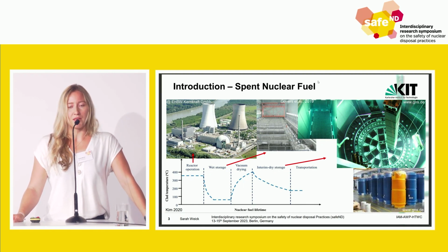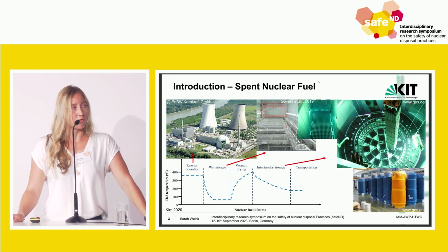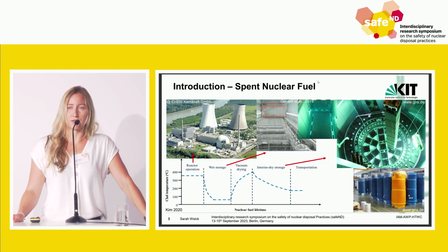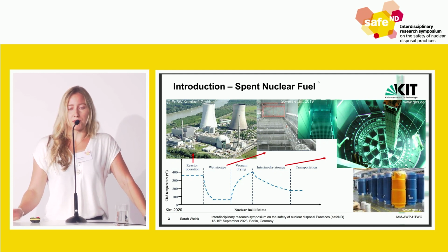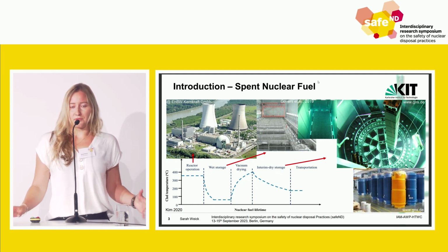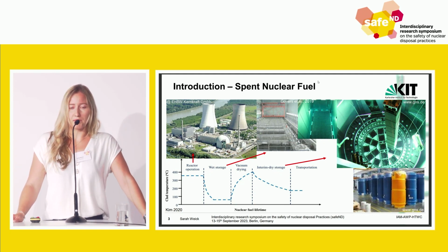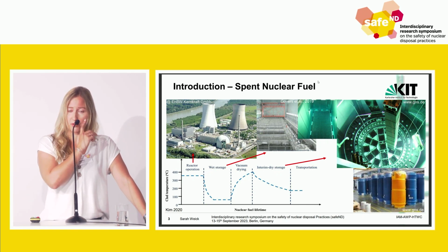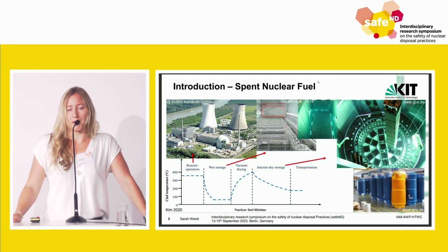It is known that we have surrounding cooling water during the operational phase that is in direct contact with the cladding tube. The spent nuclear fuel consists of this cladding tube, which takes up hydrogen due to the corrosion process occurring at the temperature during reactor operation, and this hydrogen ingresses into the material.